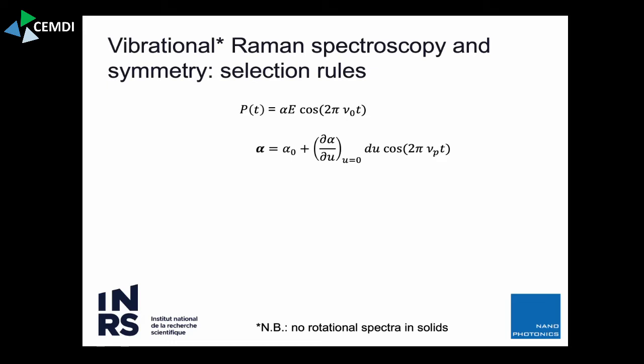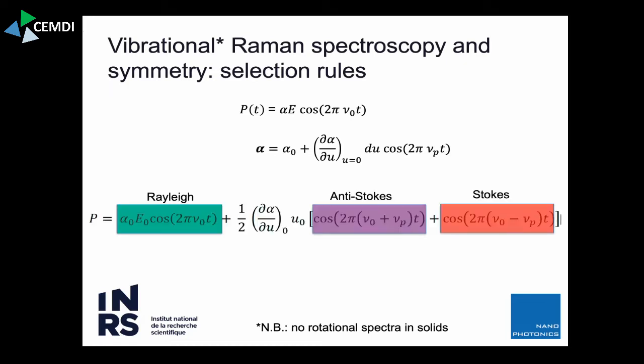And so you get a second contribution here. You get the equilibrium polarizability plus an oscillating part that changes at the speed of the vibrations in the sample, at the frequency of phonons. They are typically 2 orders of magnitude below the frequencies of optical frequencies, sorry. So if you insert this alpha into this equation, you see that you're mixing the frequencies, and you get a first term, which is the elastic Rayleigh term, and you get a second term, the sum term, and the difference term, which is the Raman effect, Stokes and anti-Stokes.